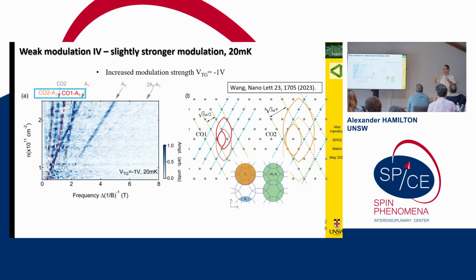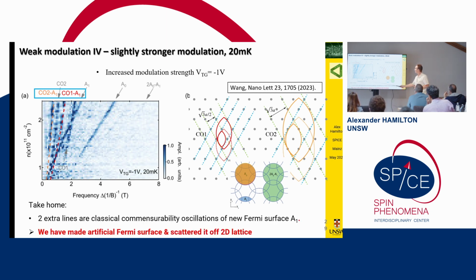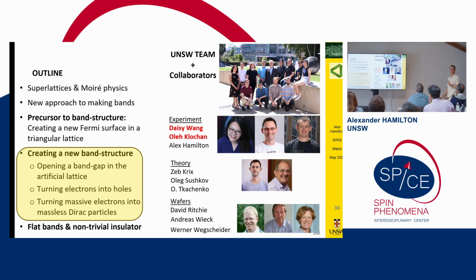Why this is nice is these 2 extra lines here are classical commensurability oscillations of this new Fermi surface A1, as opposed to commensurability oscillations that we saw previously of that original Fermi surface A0. So I'm scattering a new Fermi surface off an artificial 2D lattice. So I would say that's evidence that I've created a new Fermi surface. But it is not evidence that I've created a new electronic band structure. So that's what I'd like to do next. I'd like to create a new band structure.